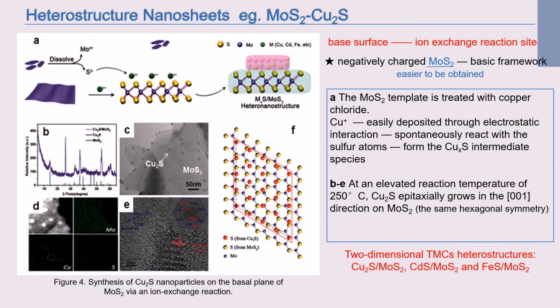Then it comes to the heterostructure nanosheets. Typically, the synthesis of cuprous sulfide on the basal plane of molybdenum disulfide via an ion exchange reaction. In the synthesis of heterostructure nanosheets, the base surface can be used as an ion exchange reaction site, and the negatively charged molybdenum disulfide is used as a basic framework, for it is easier to obtain compared with some other TMCs.